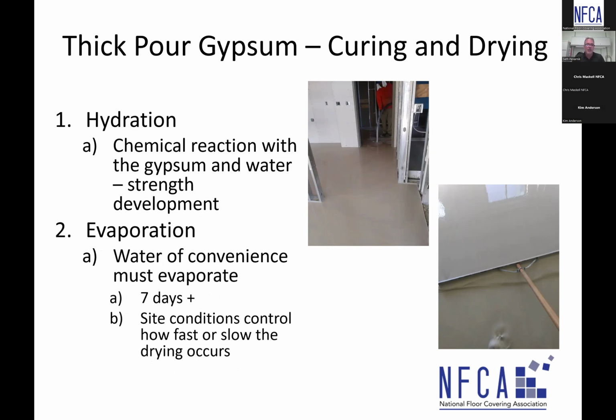Evaporation takes time. It's very common that we're at least 7 days of evaporation before the thick pour gypsum is ready for flooring. But site conditions are going to control how fast or how slow drying occurs. It's no different than anything that's being installed on a job site that has water in it. Your adhesives that you comb out, maybe a pressure sensitive adhesive that has to go dry to the touch, it's no different with those products going dry to the touch. Different site conditions are going to control that. If you have cooler temperatures, things take longer to dry. If you have warmer temperatures, things can dry quicker.